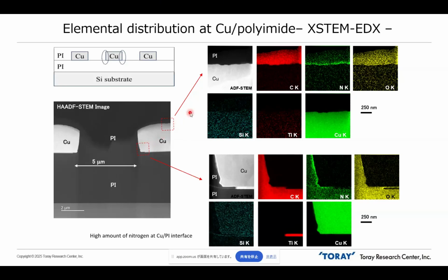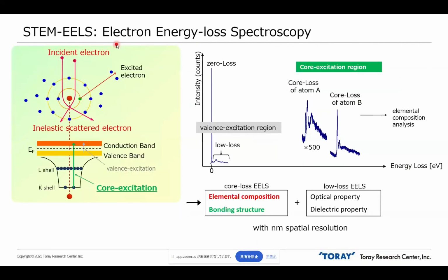At first, we examined the elemental distribution using the conventional STEM-EDX technique. Then we can find higher nitrogen intensity around the interface between copper and polyimide, on both the upper surface of the copper and the side edge of the copper. But in this case, EDX shows elemental composition distribution, but we cannot get any other information from these results because EDX is just elemental composition analysis. So as a next step, we use this technique, electron energy loss spectroscopy.